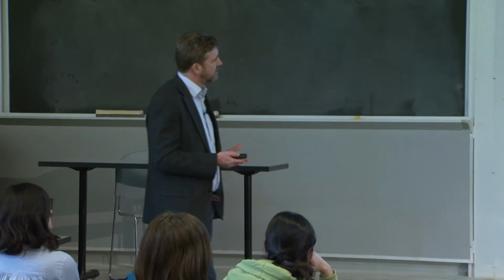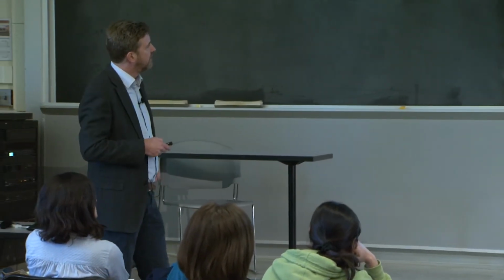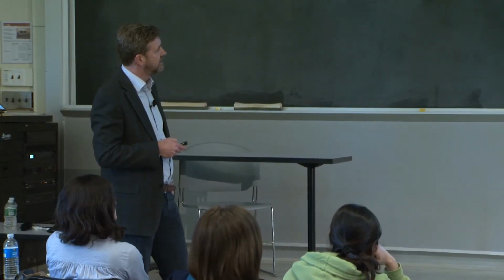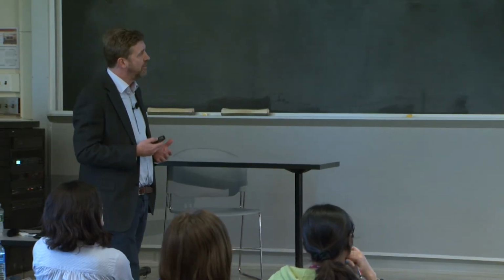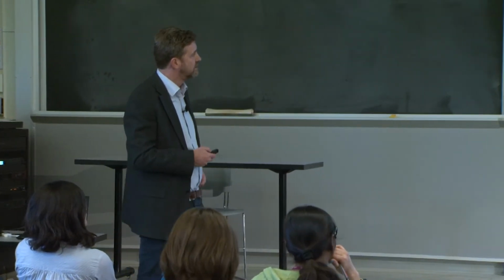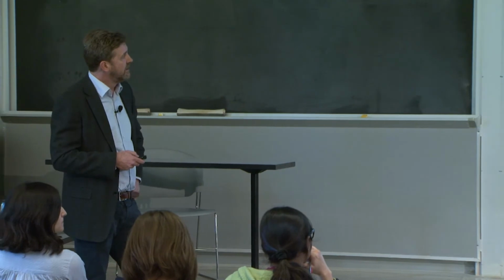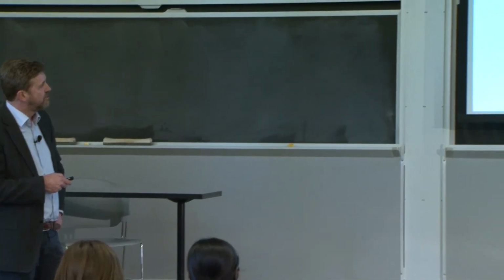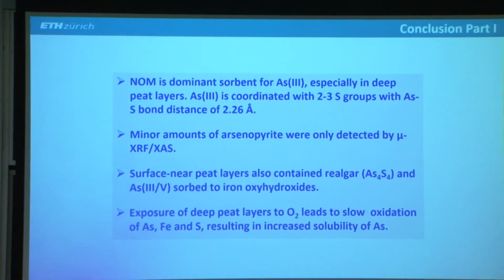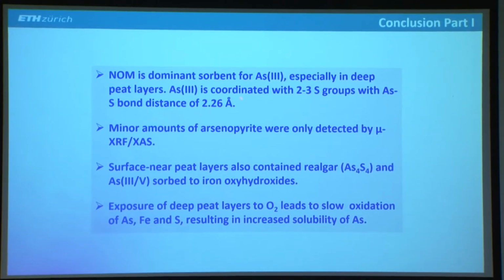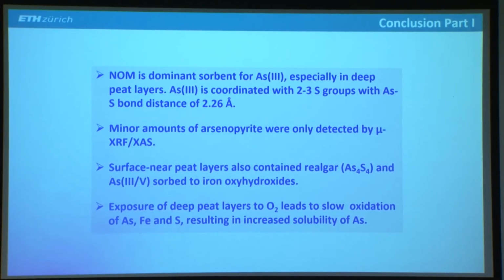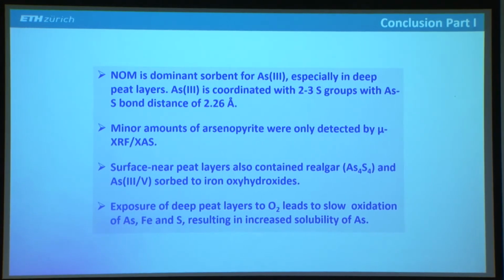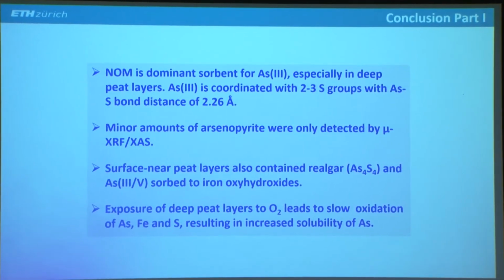So the conclusions of this part are that the natural organic matter is indeed a very dominant sorbent for arsenic-3, especially in the deep peat layers. And in this, arsenic-3 is coordinated with 2 or 3 sulfur groups with this arsenic-sulfur bond distance of 2.26 angstroms, which is consistent with our references.